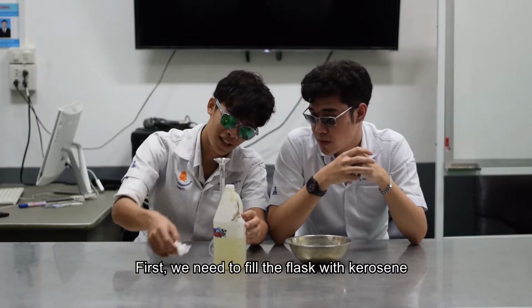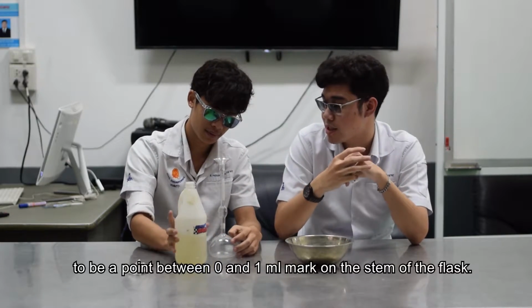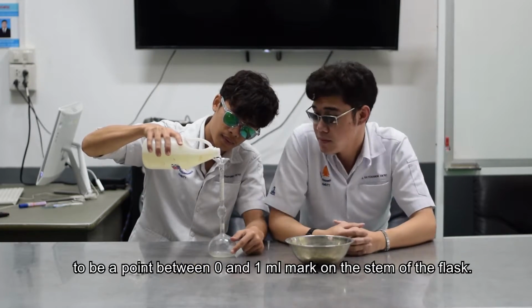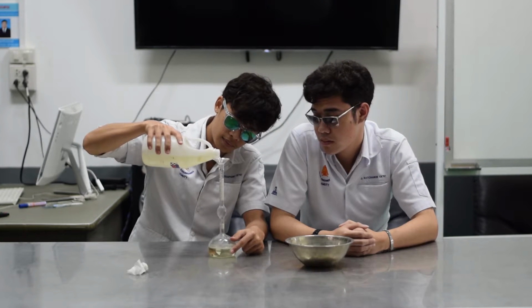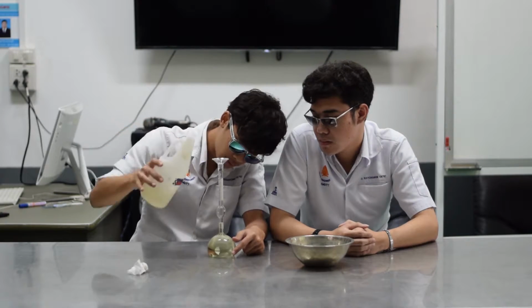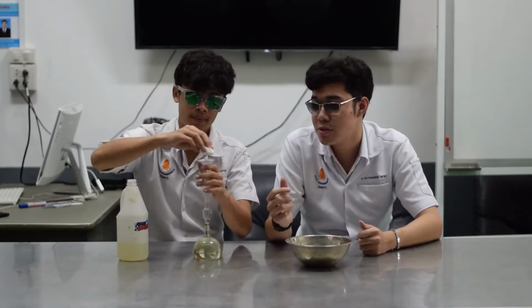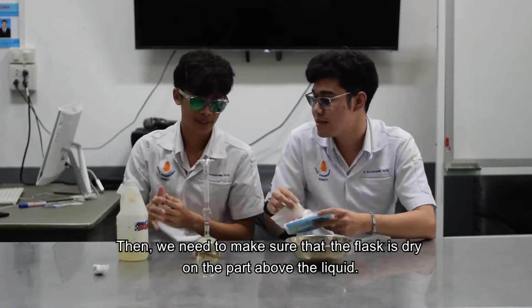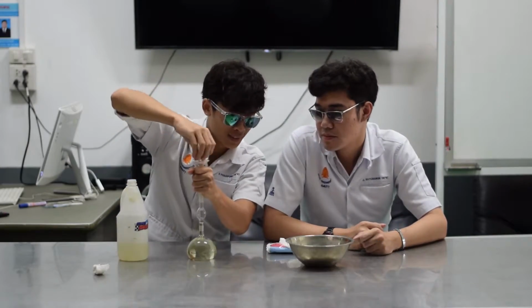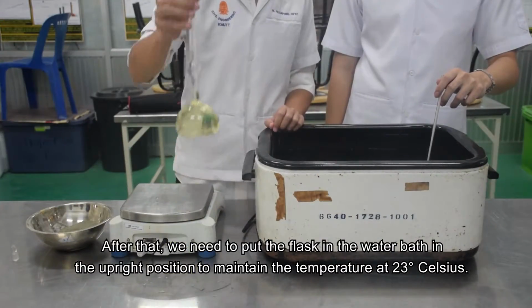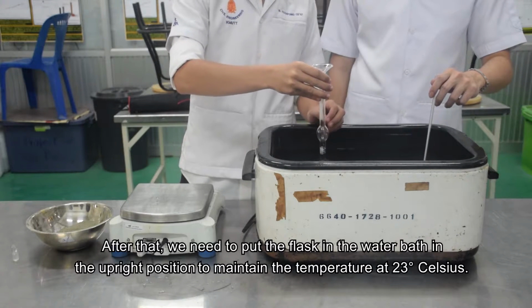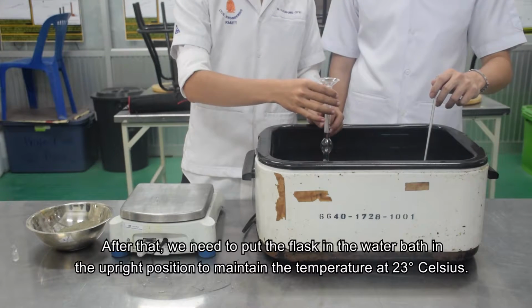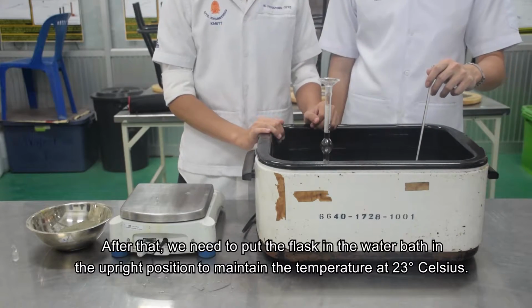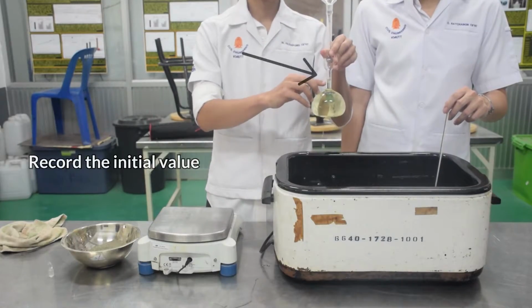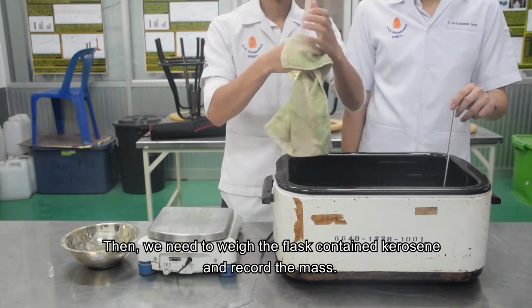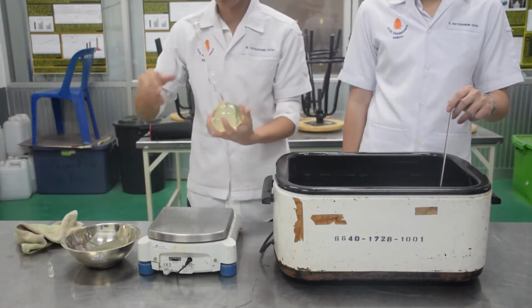First, we need to fill the flask with kerosene to a point between 0 and 1 milliliter, marked on the stem of the flask. Then we need to make sure that the flask is dry on the part above the liquid. After that, we need to put the flask in the water bath in the upright position to maintain the temperature at 23 degrees Celsius. Then we weigh the flask containing kerosene and record the mass.